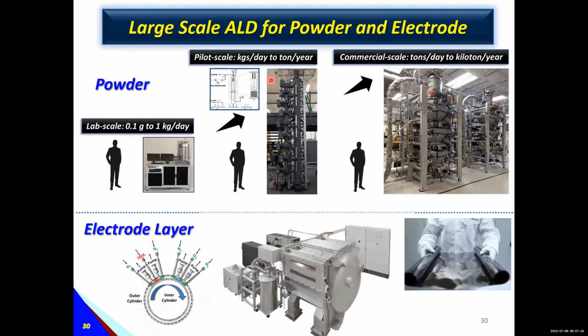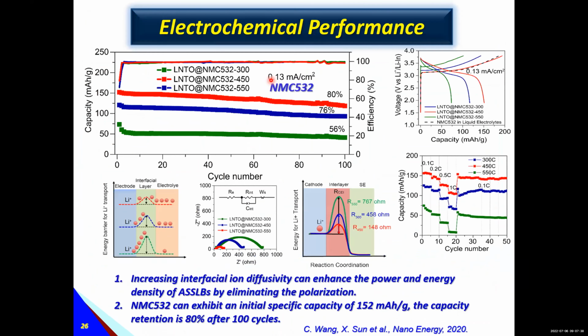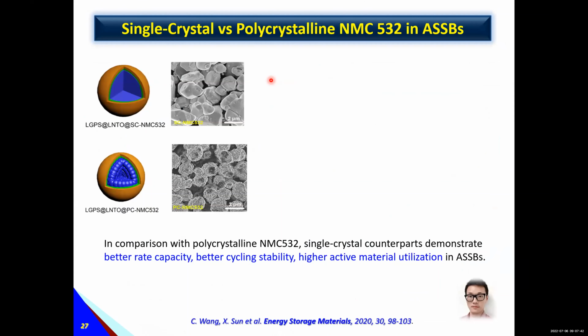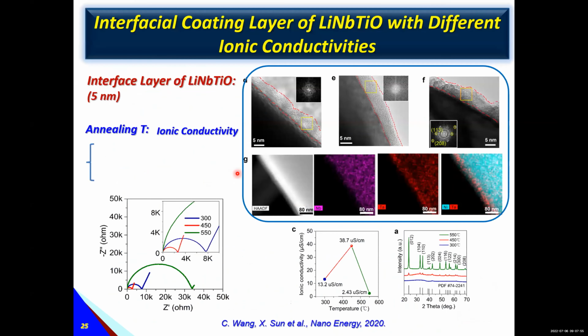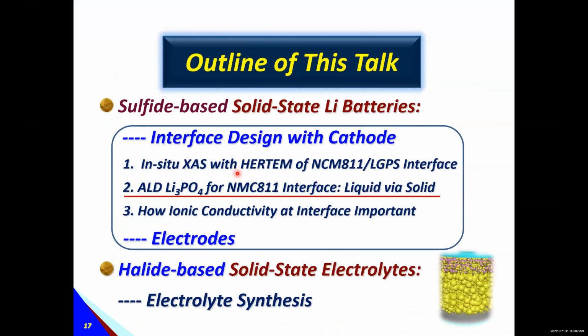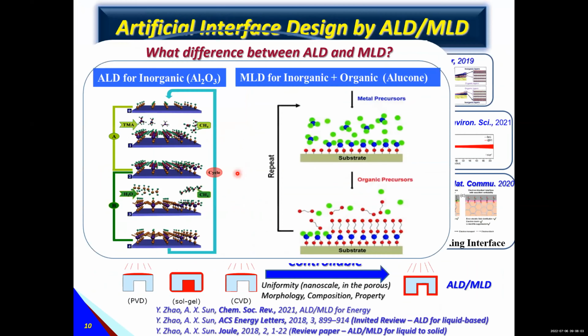Yes. So actually, here we talk about the ALD process. When we talk about single crystal or polycrystalline, the advantage of ALD is that we can deposit coating uniformly in polycrystalline everywhere. It depends on the mechanism of ALD, which is diffusion, and also depends on the functional groups on the surface. So with this process you can deposit everywhere, even in channels or holes. So for polycrystalline, we should see they can deposit everywhere.